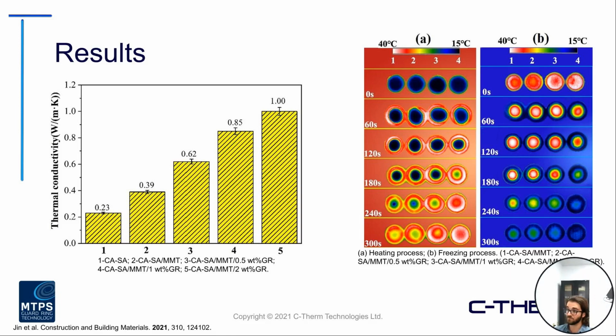Once they prepared these samples, they did various thermal imaging. On the right here, looking at the A column at the 240s mark, you can see that through the increased graphene content, the material goes into the liquid state much quicker. Going from blue to that reddish white, you'll notice that the highest concentration of graphene was able to transfer that heat much more efficiently throughout the bulk of the material.